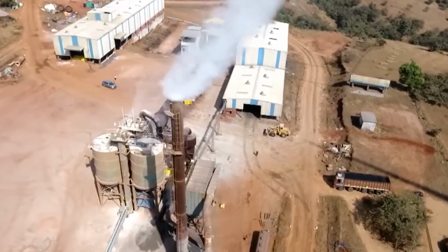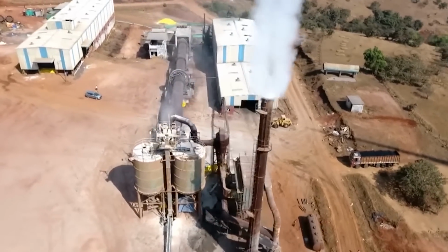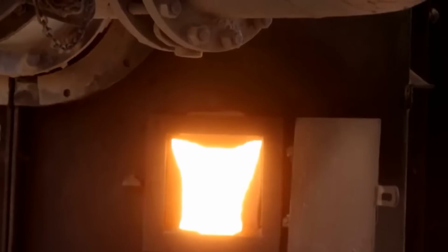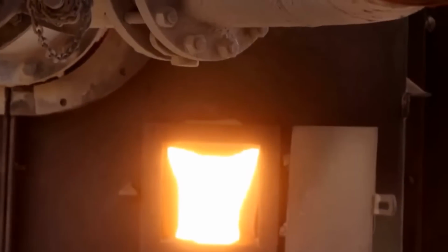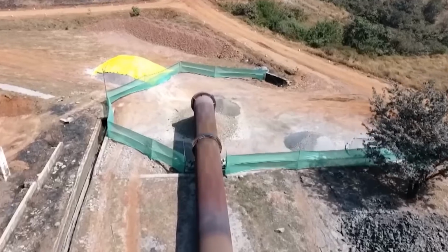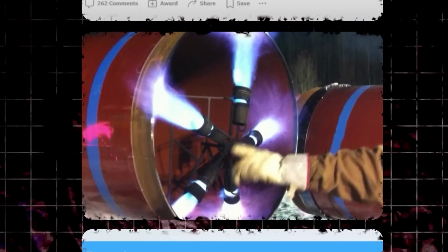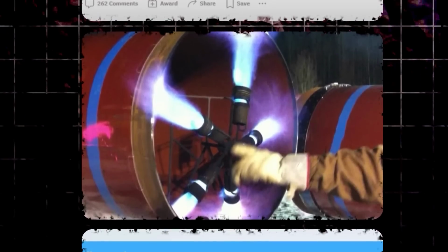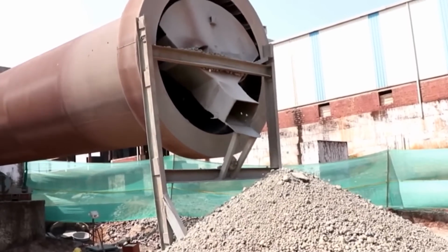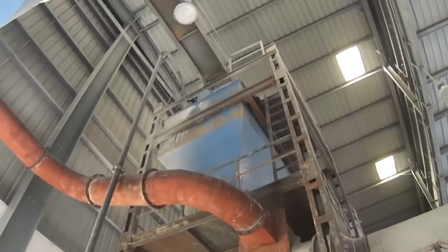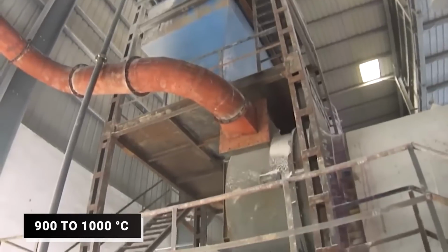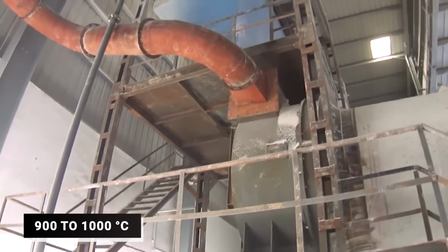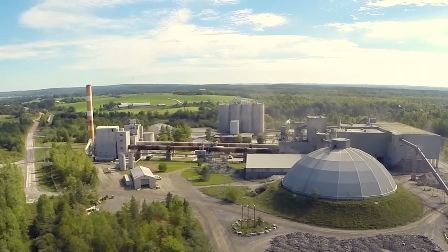Preheating the raw meal is crucial as it reduces the energy required in the rotary kiln, making the entire process more efficient. By preheating, the raw meal is better prepared for the high-temperature processing that follows. Once preheated, the raw meal moves into the calciner. Here, at temperatures around 900 to 1000 degrees Celsius, significant chemical transformations occur.